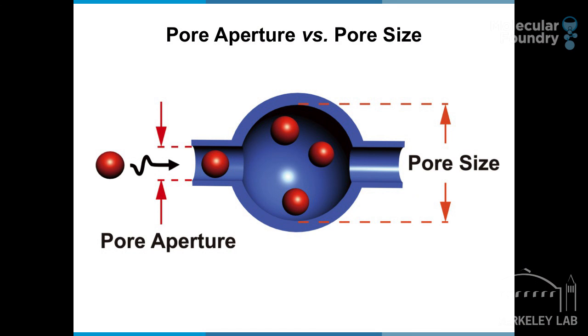For quite some time, the challenge in making porous crystals has been how do you make progressively larger and larger pore openings. In all the MOFs I've discussed so far with you, relatively small molecules can go into the pores because the openings are not very large. They're on a nanometer scale. Could we make porous crystals, MOF crystals, that have openings as large as proteins, so that proteins can go in, and we can therefore develop the chemistry of proteins within the pores? Let's say we can operate on larger molecules and develop the chemistry of larger molecules within the pores of MOFs.